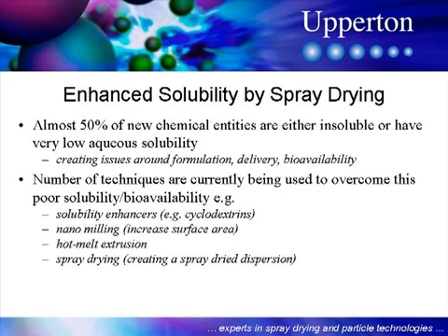Some recent examples include the use of solubility enhancers such as cyclodextrins, nanomilling, which breaks up the drug into small nano-sized particles to increase surface area, hot melt extrusion, and more recently spray drying and creating a spray dried dispersion to improve the solubility of poorly soluble drugs.